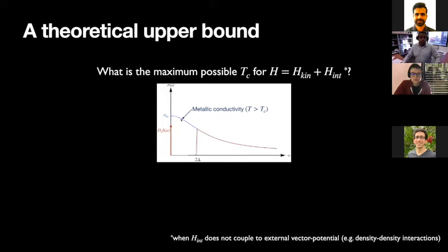But what we know is that once this metallic state turns into a superconductor, and for the purpose of this discussion, we can assume it's a fully gapped superconductor, there's a gap of 2 delta. This is a 2-particle response, below which there is no spectral weight. Now the total spectral weight, meaning the area under the full optical conductivity, is conserved.